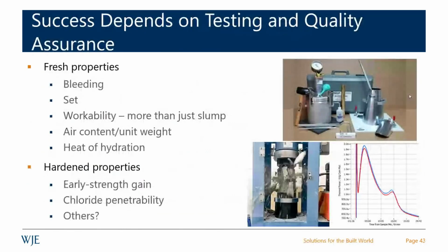So, kind of wrapping up now, I just want to talk about testing and quality assurance. The one thing to note is that as we switch to different mixes, different cementitious systems, as we start to reduce our cementitious content, you will get differences in the fresh concrete properties. The amount of bleeding, the rate of bleeding changes as we move towards more finely divided cementitious. Set times can be changed. It can be more sensitive to temperature. Workability, it's not just slump.